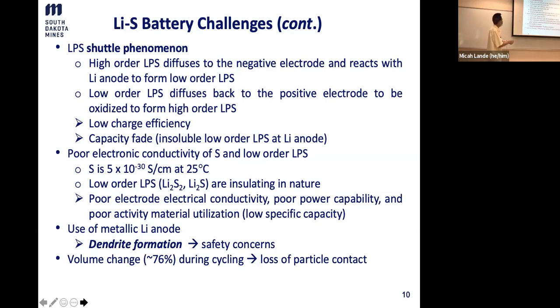So that leads to capacity loss. And then another thing is that sulfur is not a very good conductor. So you can see here very, very low conductivity, and also the lower order, the final products, are insulating by themselves. So that leads to, let's say, very poor power capability.